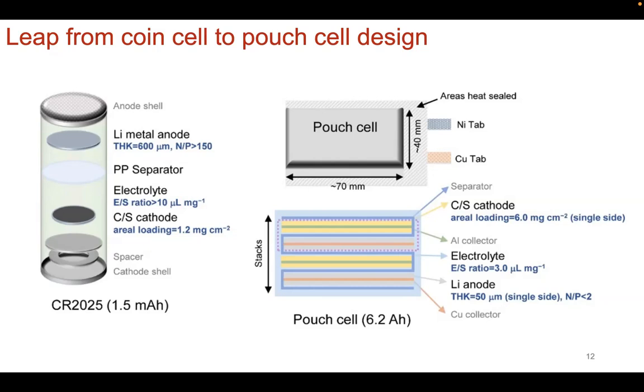encounters problems that you wouldn't have had before, which is limited capacity because you just don't have enough electrolyte to really permeate the sulfur or the specialized carbon order structures that you have. And so your capacity just drops way off because you're running so lean, right? So now you have to go to basically scaffolding design that would allow the diffusion of the liquid electrolyte more efficiently to get to the sulfur. So the materials design for, let's say, coin cell testing, where you would not have had these issues before, now you have to actually solve them when going to pouch cells.